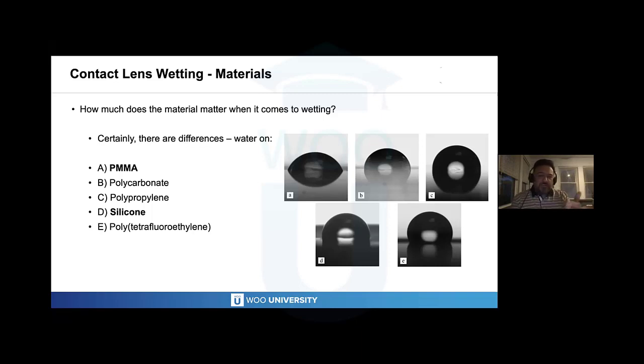As you move across and look at the other pictures here, the one that I wanted to point out is letter D, and that's silicone. What allows our modern GP materials to be breathable is the addition of the silicone, which creates oxygen permeability, but it does so at a price. You can see what happens with silicone when we add water to it. That wetting angle suffers in the process.